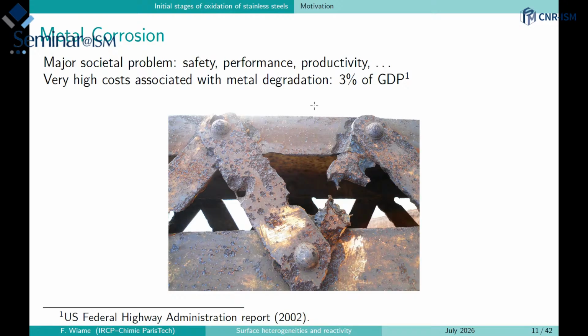So obviously, we are not studying the structure when they are in this state of corrosion, but you can see that this is really something that can be a problem for safety. This is a bridge in China, but what you can see is that in fact the corrosion is generally starting by pitting corrosion, so a very localized problem. And the idea is to understand how heterogeneities at the surface can be responsible for this starting of the corrosion, because if we can stop this initiation, then we can prevent and significantly reduce the corrosion of this system.